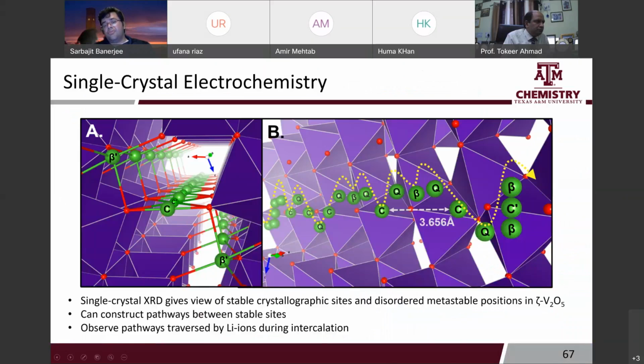And so we can refine these C, C prime and beta sites, and then we know the diffuse density of the Q sites, so we can start mapping the pathway through this lattice.